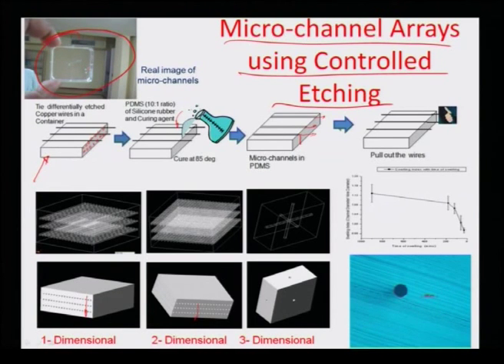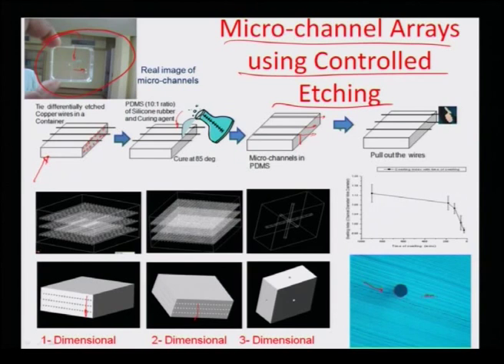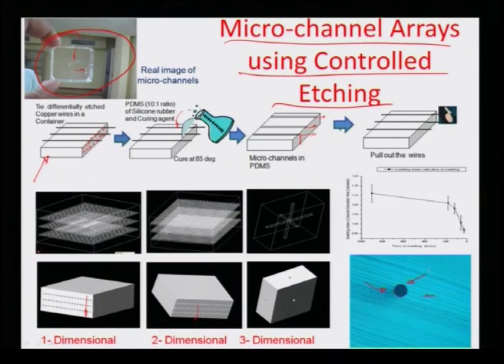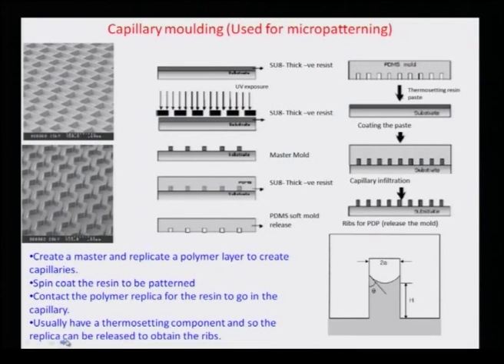You can have micro channels not only on a surface by using 2.5D lithography, but also in the bulk or volume of the PDMS. Looking closely at the figure, you can see a crisscross channel created within the volume of the block — one channel in one direction and another in a perpendicular direction. The PDMS is swelled using a solvent and then deswelled back, maintaining the aspect ratio of the structures. This is an important technique for realizing arrays of micro channels in the bulk volume of PDMS.